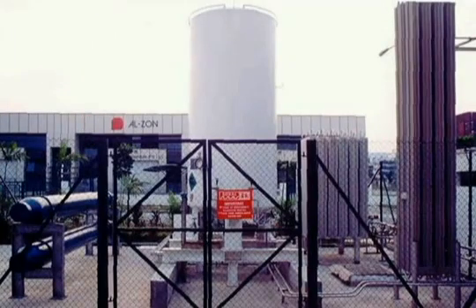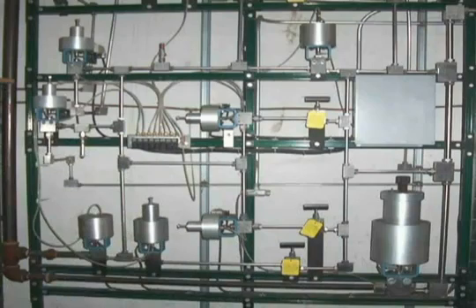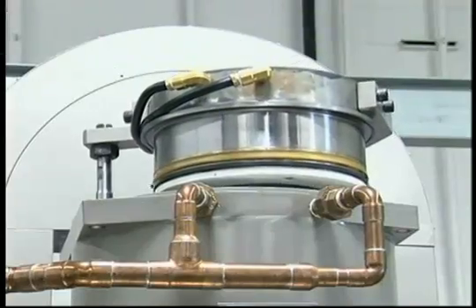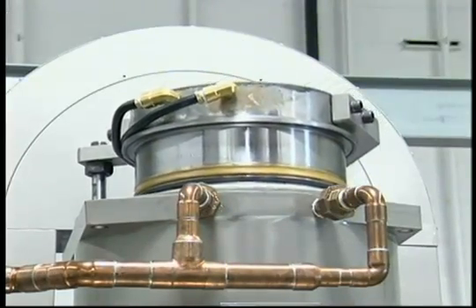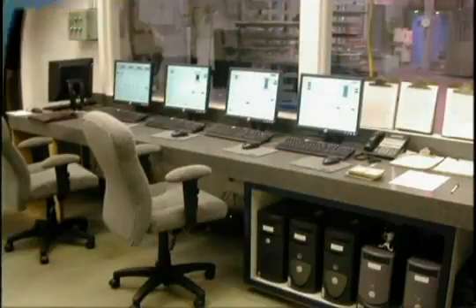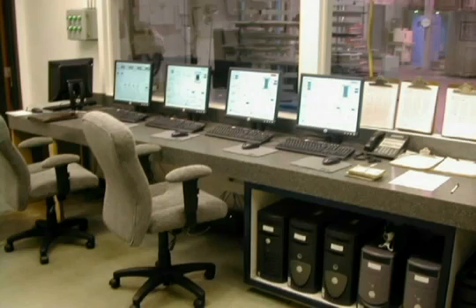The pressure medium is most commonly argon, which is fed from storage cylinders to an electro-hydraulic intensifier that pressurizes the gas to the required level. A system of high-pressure feed and vent valves controls the flow of gas to and from the pressure vessel. The self-sealing vessel closure assembly is lowered into place, and from this point on, the press is typically controlled by a computer, which follows a recipe programmed by the user.